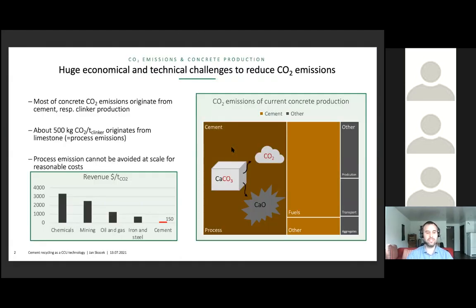As also partly commented by my preceding speakers, concrete, especially the cement, is responsible for a significant amount of CO2 emissions, some 6 to 8% worldwide, depending on how it's accounted. And the biggest challenge of cement and concrete is the part of the emissions coming from clinker production, the part which is coming from limestone. Limestone is the raw material used to provide the calcium oxide, which is the reactive component of the clinker of the cement, and there is no alternative to calcium carbonate. As a result, for every ton of clinker which we produce, we emit half a ton of CO2, and as mentioned, there is no substitute for this.